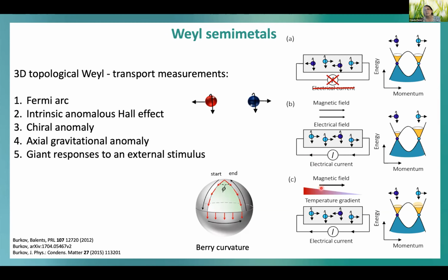And instead of a voltage, you can also apply a thermal gradient. There was a prediction by Subir Sachdev - it's more or less the same as the chiral anomaly, a thermal chiral anomaly, that this reflects the axial gravitational anomaly in astrophysics. So in general, because of the Berry curvature, we expect also giant responses to external stimuli.